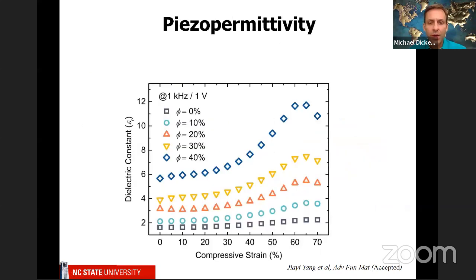The other thing we observed that I think makes this work quite interesting is we went back and measured the dielectric constant, which was reported here as a function of strain. Now, if you just take pure silicone that you can buy in a commercial kit, you'll see this, it's got a very low dielectric constant and it doesn't really change very much with compression. However, if you start adding liquid metal, so as you move up all the way to here, this is 40%, you'll see that the dielectric constant goes up at zero strain, but it also changes as you compress it.